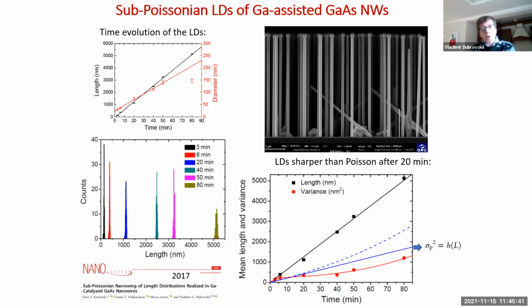and we can also observe sub-Poissonian length distribution of gallium catalyzed gallium arsenide nanowires, like for instance in this paper, and we also published another paper with Emmanuel Dimakis. The droplet preparation techniques were different, but what we see is that under optimized conditions, after some time, we can observe a length distribution which is narrower than the Poissonian, which is of course amazing. And this is due to the effect of nucleation anti-bunching, as Frank explained in his talk, which results in sub-Poissonian sharpening of the length distribution.